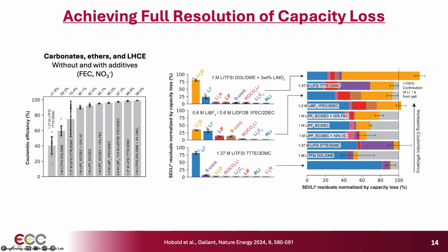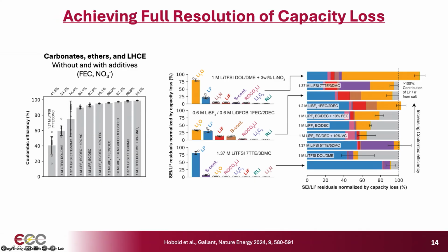So we get this kind of informative fingerprint, if you will, of where the capacity is being stranded in these cells. So one thing I want to start by emphasizing is that in some of these cases, we could resolve for the first time 100% or close to it of the capacity loss in the sample. So that's really a marked improvement from where we started out. The second thing you can do is start to pull out some trends by eye. So for example, going from lower to higher Coulombic efficiency, you see less of this blue here, which is dead lithium. So decreasing dead lithium leads to higher Coulombic efficiency. This is already known in the field, and our results also validate it. But you also see increased prevalence of this orange here, which is lithium oxide.